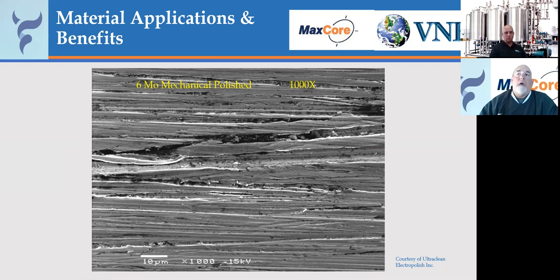So you still have the same issue: if you allow this grinding swarf to get into the system, it will create rouge within the system. A lot of times people say, can't I just passivate that and remove it? Yes, a lot of times it will. But on mechanically polished surfaces, if everyone will remember, probably 4 or 5 years ago, everybody was having a real problem with black residue on the surface of their steel. They'd clean it, go back a couple days later, run a white cloth across it, and have a black residue on it. That was grinding swarf coming out of the striations, and that will continue to bleed out over time. Passivation will help to remove it, but it won't remove it all.